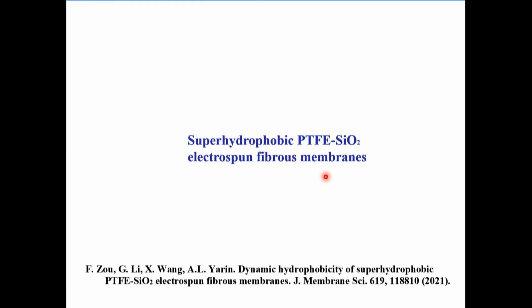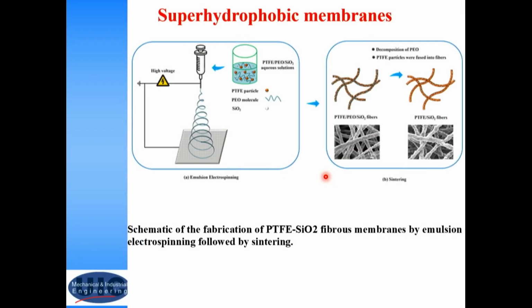So let me start with the superhydrophobic Teflon-glass electrospun fibrous membranes. Glass was already mentioned yesterday by Professor de Klerk in her work, so it looks like it becomes a popular topic, introduction of glass in nanofibers. So that's what we have tried to do. So we organized electrospinning of a blend of essentially Teflon, a little bit of PEO for spinnability, and glass particles. Now, the idea is to make, ultimately, fibers which are superhydrophobic. This is number one, and also to enhance the superhydrophobicity not only by the chemical nature of Teflon, but also by roughness introduced by glass beads which are inside.